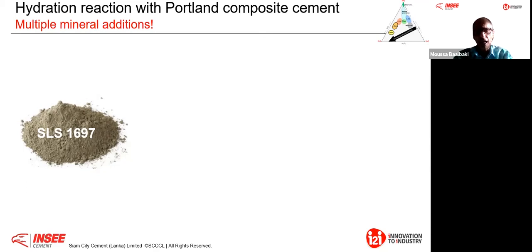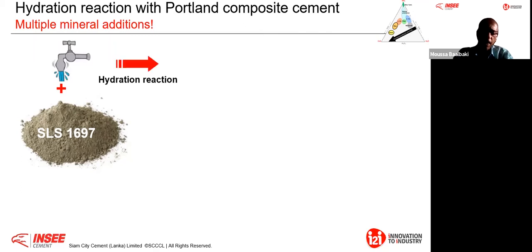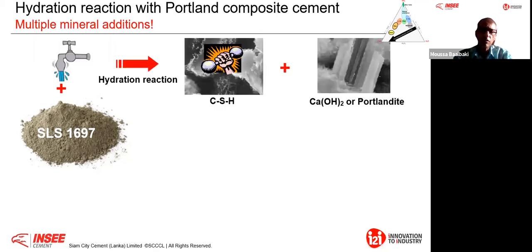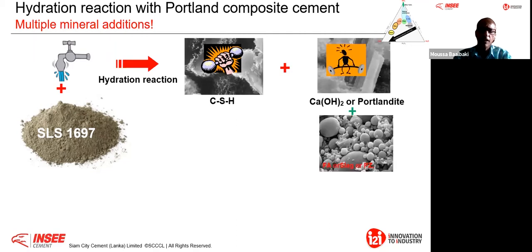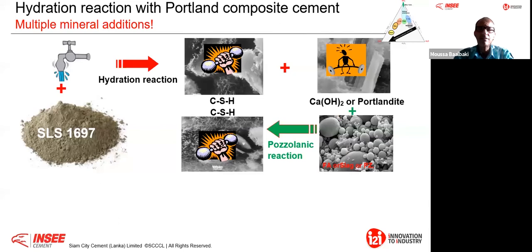Now, when I come to the SLS 1697, here you see we have multiple mineral additions. It's not 2, we can have 3, we can have as many as we have on the table. Now here you have clinker, therefore again you have the same reaction with the two products, giving you strength and weakness. Of course, one constituent, for example, could be slag, another constituent could be fly ash. This, as I said, is aluminosilicate, therefore you have the SiO2. This SiO2 will combine with the calcium, again from the pozzolanic reaction, you get more strength and you mitigate the weakness. But it's not finished, because you remember what I told you.